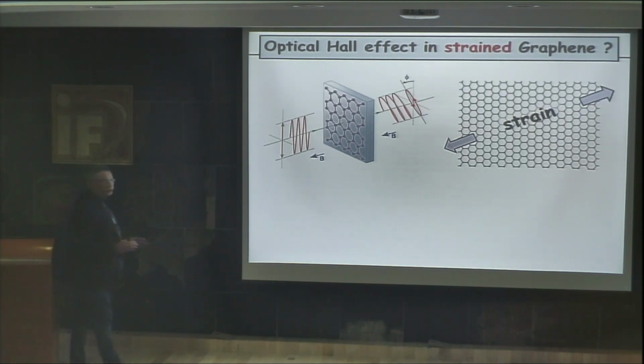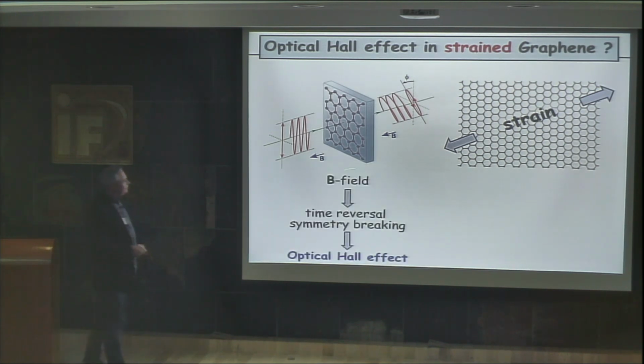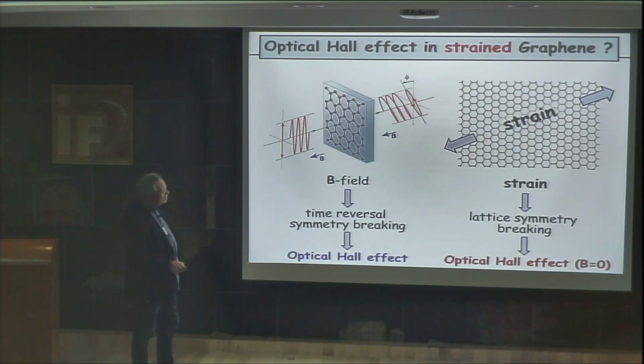But in our case, we do not want to use a magnetic field. The magnetic field in the system leads to a time reversal symmetry breaking, which induces this optical Hall effect. In our case, we want to suppress the magnetic field, but we want to use strain instead in order to produce the same effect. The strain in graphene induces a lattice symmetry breaking instead of the time reversal symmetry breaking of the magnetic field. And in this case, you could also have the optical Hall effect, but without the presence of a magnetic field.